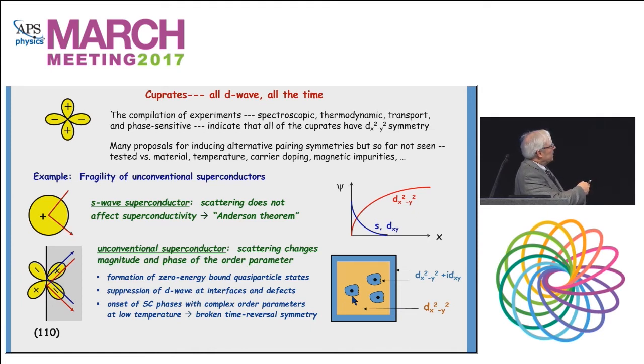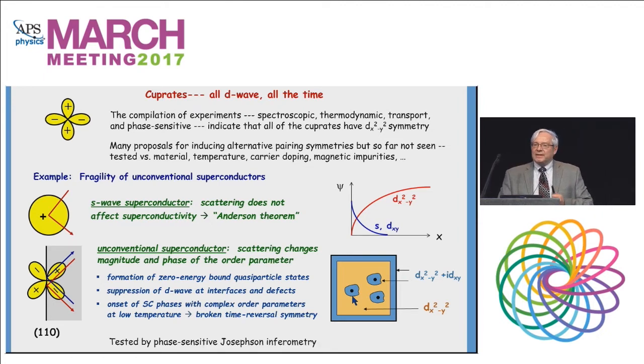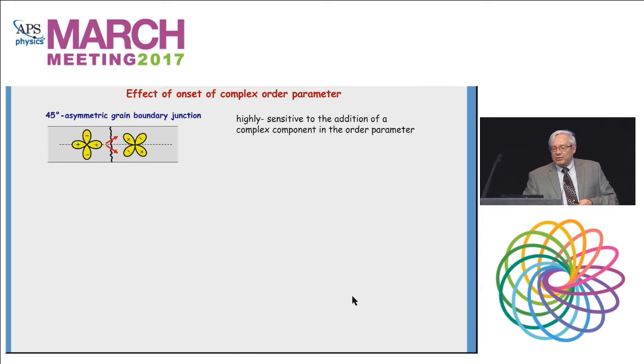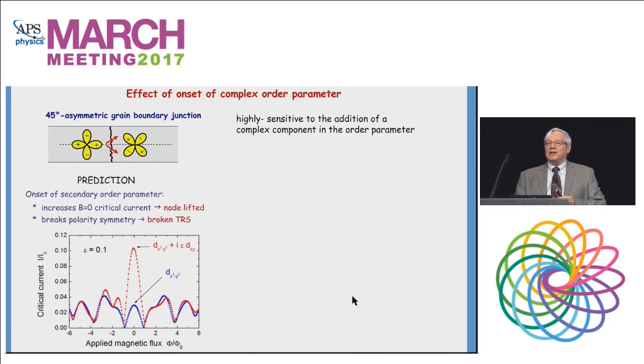When the D-wave order parameter dropped, there would be some other term coming in, a complex order parameter. We were able to test that actually with Josephson interferometry. This is an experiment where we used the asymmetric grain boundary junction. The prediction was that even a very small amount of complex order parameter would give you enormous change.